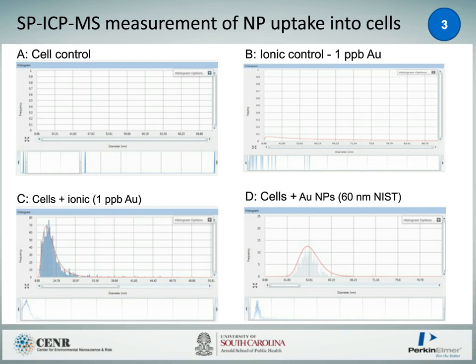And then if we look at D, where we had cells plus gold nanoparticles, in this case they were 60 nanometer, we exposed to around 1 ppb again, which is about 500,000 nanoparticles per mil, and we had cells at about 1,000 cells per milliliter. And you can see that we're getting a nice even distribution as you would expect from a nanoparticle, so these cells have actually taken up nanoparticles.